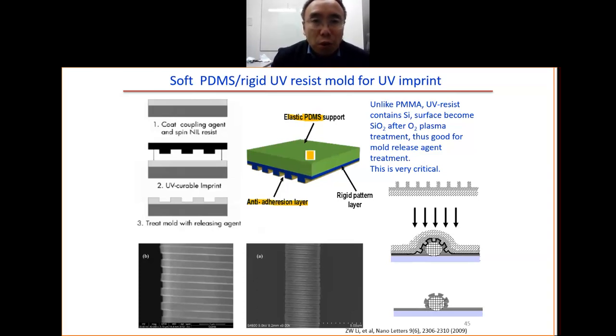So how do you make this mold? First you coat the coupling agent and then coat the imprint resist. This is the PDMS. You coat the coupling agent because the resist has low surface energy. With the coupling agent, you get better adhesion of the resist onto the PDMS substrate. Then you do the UV imprint. This layer here is the UV curable resist. You do the UV imprint, they separate, you get the mold. So you can see it's not difficult to copy the mold from the master mold onto this polymer mold.